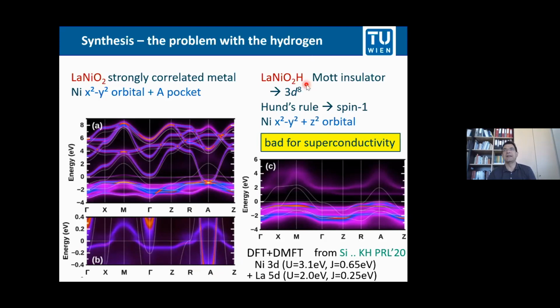If you go instead to the nickelate with topotactic hydrogen, you have one electron less on nickel, so you have a 3d8 configuration, and then Hund's rule coupling becomes very important. It means you form a spin 1 of the 2 holes you have, and these 2 holes also prefer to occupy different orbitals. In the calculations, it turned out it's the x squared minus y squared and the z squared orbitals that are occupied. This spin 1, 2 orbital and 3-dimensional electronic structure is very bad for superconductivity. And as you see here, the undoped compound even is a Mott insulator in this case.